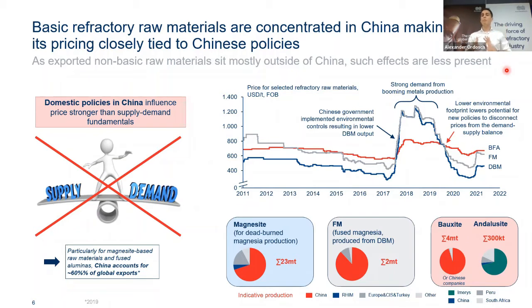Basically, it only matters what the Chinese domestic policies are doing, because as you are most likely aware, nowadays, China produces the lion's share of almost anything. When we look at steel, they produce 45%. In cement, they produce more than 50%. And with refractory raw materials, it is exactly the same. So we see here at the bottom of the slide 4 different raw materials. And let's start with the magnesite, so the dead burned magnesite production. About 70% of the global production is in China.